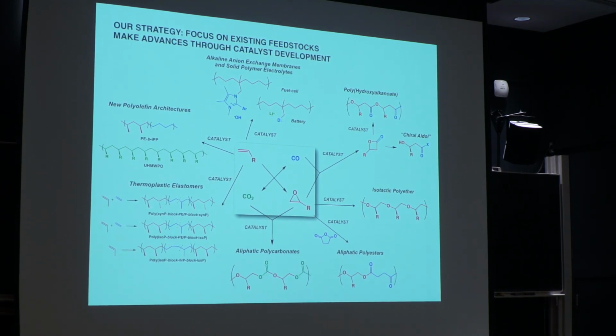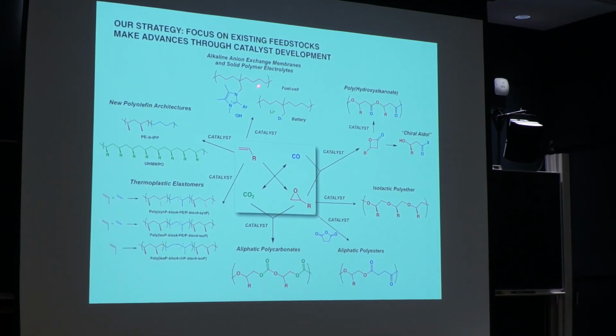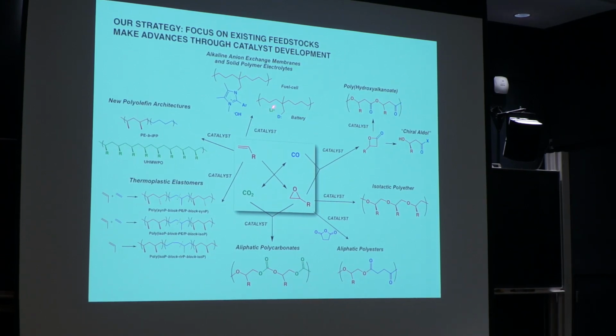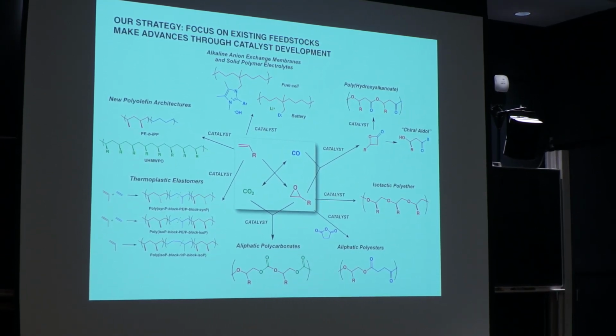the optically active epoxides. I haven't told you anything about this area of polymerization of epoxides with cyclic anhydrides. And here you can get a range of materials from very soft, low Tg materials to very crystalline materials to very high Tg materials. And these are aliphatic polycarbonates, and so these all will biodegrade in the environment. We do a lot of work with polyolefins. I just told you about some of the block polymers, but we've got a big program on making thermoplastic elastomers. And then the emerging area over the last 5 to 10 years in my group is making polymers that are used for energy storage and conversion.